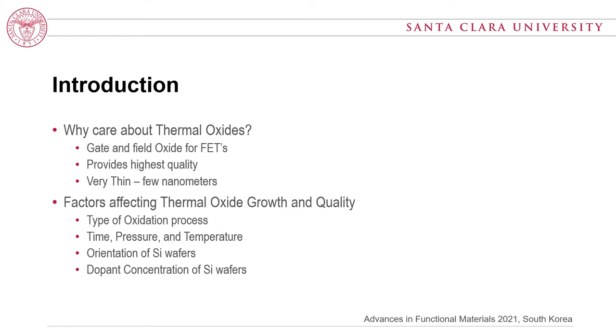The next factor is how long the oxidation is carried out, which is the time, and at what pressure the oxygen is introduced — that's the pressure — and then at what temperature. The orientation of silicon wafers also matters; based on packing density, surface energy, and surface roughness, the orientation does affect thermal oxide growth and quality. Dopant concentration of silicon wafers is also a factor, as it affects how oxygen diffuses into the silicon.